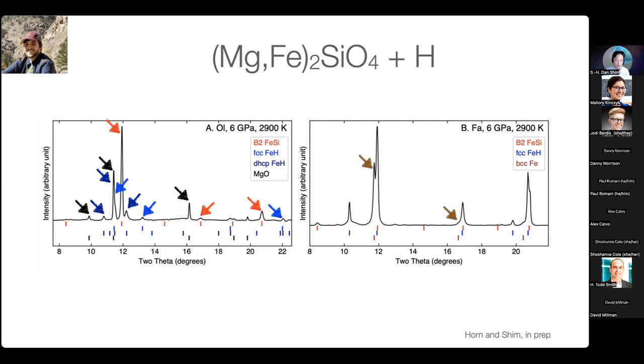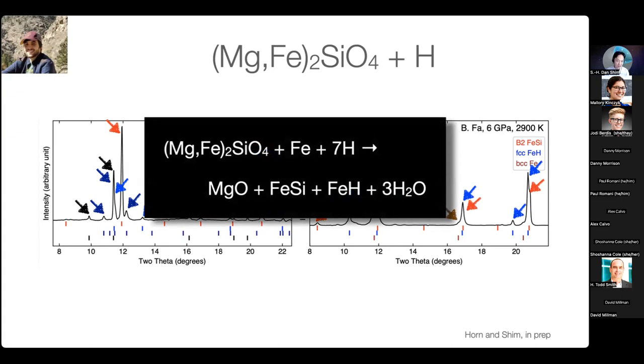We conducted a similar experiment with a very iron-rich sample, which is called fayalite, which is essentially Fe2SiO4. For that case, we observe essentially the same results, which is the formation of iron, iron hydride, and silicon reduced to metal. So if you write this observation into a chemical reaction, our experiment indicates that olivine breaks down in hydrogen into MgO, and all the iron in the olivine is reduced to iron metal and alloys with hydrogen to form iron-hydrogen alloy. Then silicon also gets reduced and alloys with the metallic iron. And because now you are reducing both silicon and iron, you can release a lot more oxygen from olivine that ultimately reacts with hydrogen and forms water.